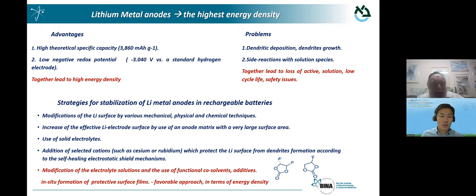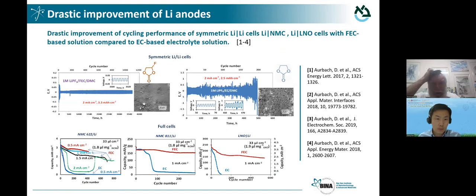We found that the simplest way is modification through the use of electrolyte solution. And when we use fluorinated solvents, we have two together, monofluorinated EC and difluorinated EC. These are very important because, with the substitution by fluorine, we can have on the active surfaces, I'm talking about both lithium and all our cathode materials, they are basic and nucleophilic. So we may have elimination of HF and then we form a double bond on the surface. So we have many options for polymerization. And now we can come up with the ideal SEI. I'll just give you experimental results, and then I'll describe what is going on, how we obtain the ideal SEI on lithium metal by the combination of these two